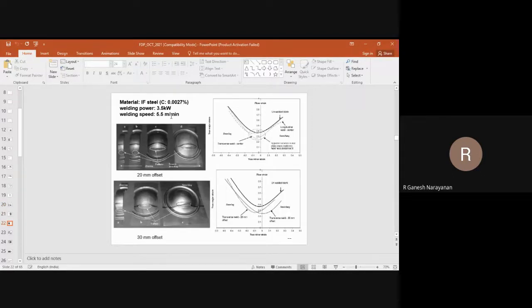Here, this is another example where weld location becomes important. Again, these are all lab scale studies. This is interstitial free steel, carbon is very low. Welding power is 3.6 kilowatt laser welding. Welding speed is used under optimized conditions. And you will see the weld can be at the center of the sample, at 20 mm offset from the center, or at 30 mm offset from the center. And they have developed forming limit curves.